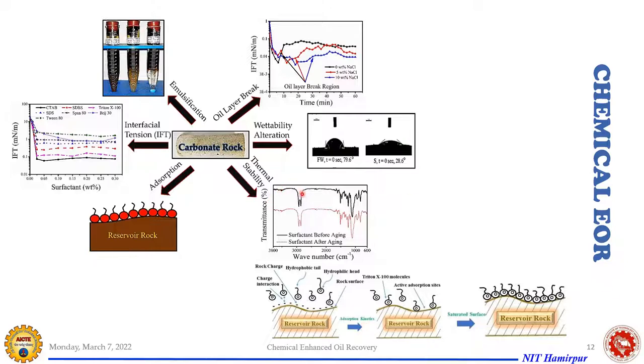So you can see this black one is the FTIR data for your surfactant, that is before aging. Once we age the surfactant at a certain temperature for certain days, expecting that the chemical would stay in the reservoir for several months, we take this out and analyze it, and you can see there is negligible degradation in the functional groups. This further says that whether you use the TG analysis, where the surfactant is exposed to different temperatures and time intervals, or this method where we have aged the sample for a certain duration and then checked it, both were saying that the surfactant was stable.